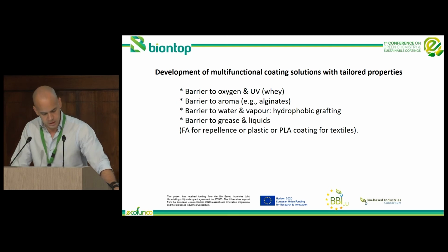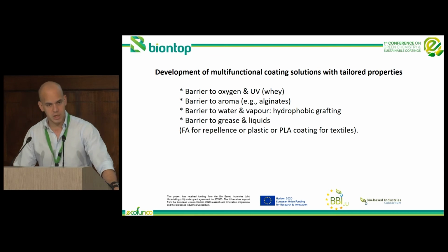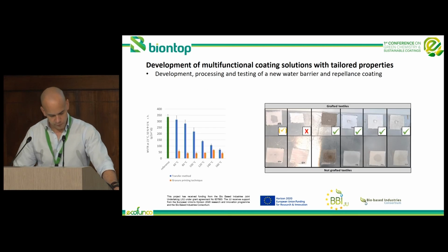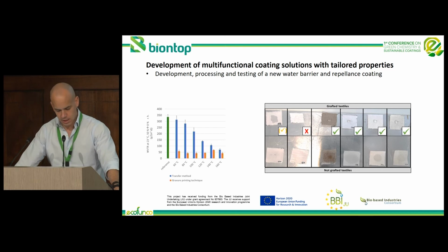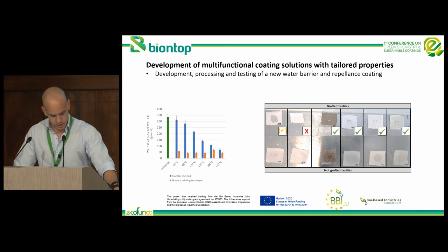So they are suitable for sensitive food and personal care applications also, and coated PLA textiles with better barriers, thickness, and hydrophobicity with water contact angle superior to 120 degrees. In first place, we are developing, processing, and testing a new water barrier and repellence coating. In order to obtain enough water barrier and repellents, we are using bio-based fatty acid through solvent-free grafting.